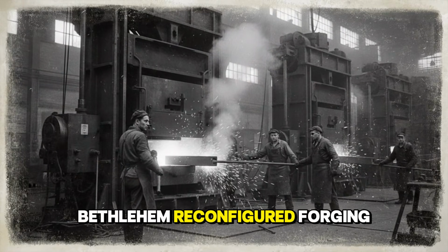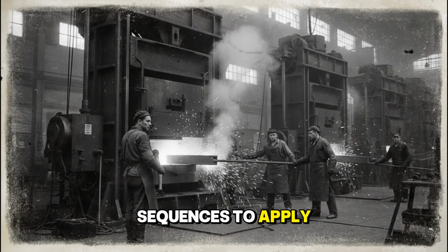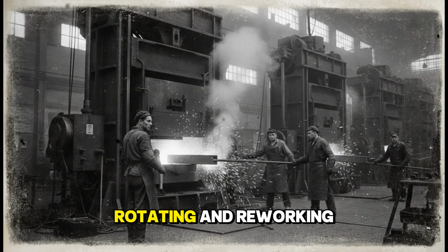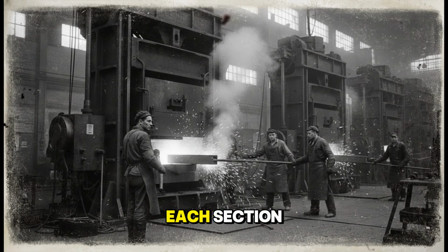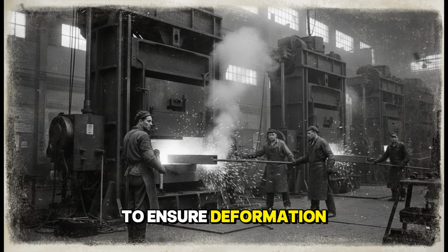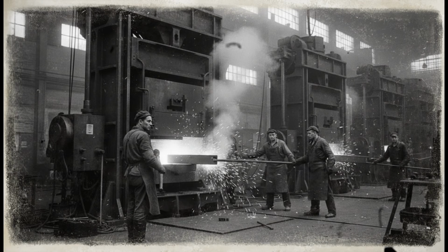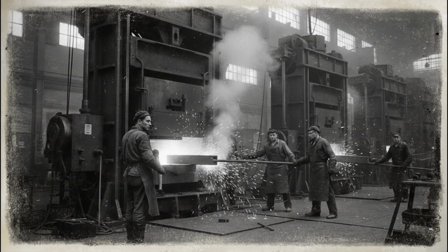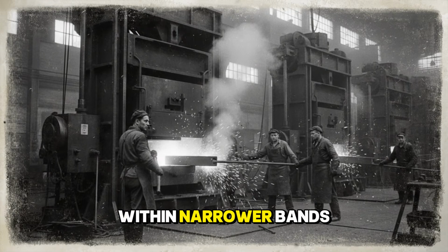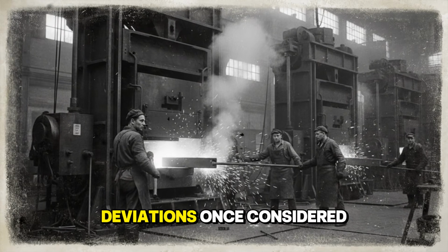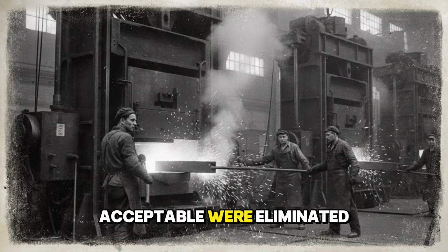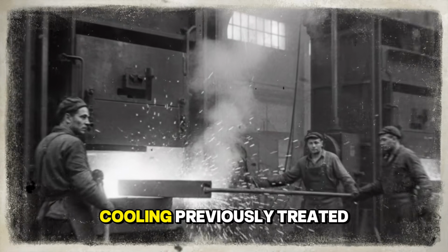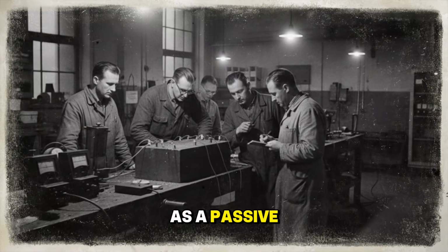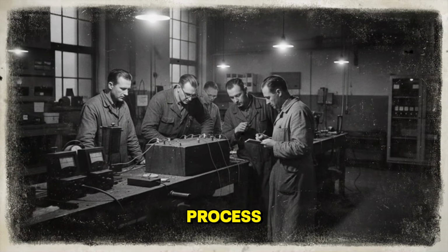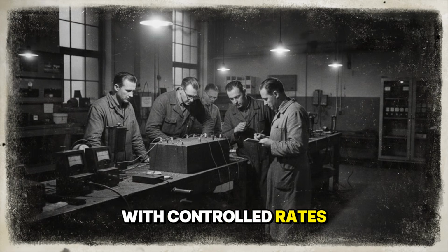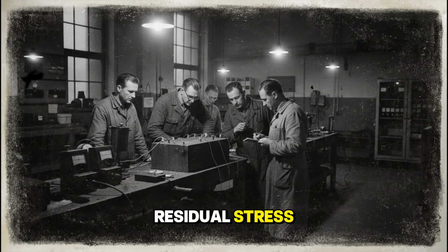Bethlehem reconfigured forging sequences to apply pressure in stages, rotating and reworking each section to ensure deformation penetrated the core. Press cycles were extended. Temperatures were held within narrower bands. Deviations once considered acceptable were eliminated. Cooling, previously treated as a passive step, became an active process with controlled rates designed to prevent residual stress.